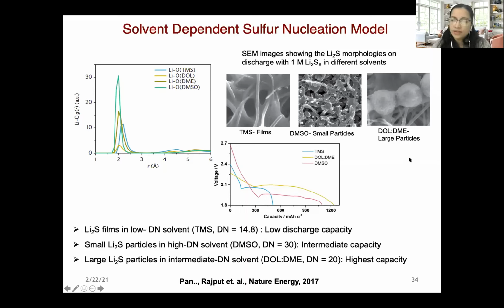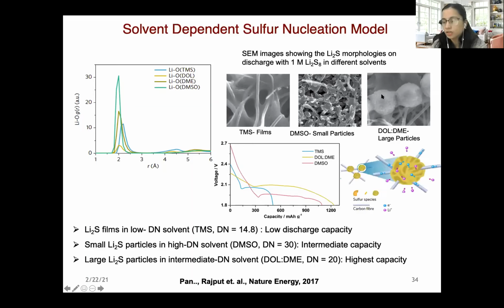And we found that for a combination of DOL-DME solvent, which has an intermediate donor number of 20, we are forming these large spherical particles, which forms an electron and lithium ion conducting network, because of which the discharge capacity is highest. And I would like to mention here that the nucleation phenomena during electrochemical process is a very, very complicated phenomena.